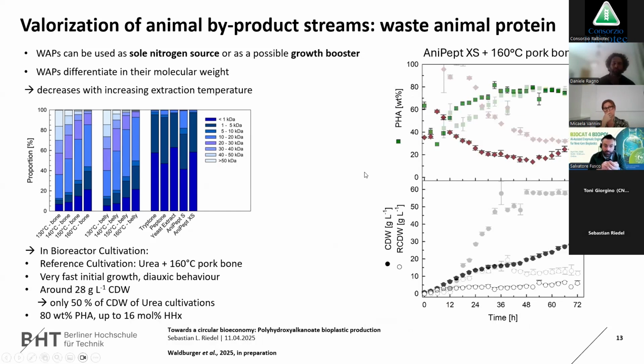So for example here, in the shadow you see the reference cultivation with urea as a nitrogen source, and here only with protein hydrolysates. What we see is that at the beginning we have faster growth with the richer nitrogen source, but then later it slows up. So maybe this can be used as a booster at the beginning, but this is still ongoing.